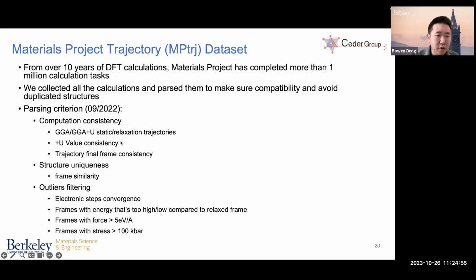And here is a list of the complicated parsing criteria that we used last year to parse this dataset. Basically, we ensure computational consistency; for example, we don't want different functionals to have inconsistent calculations, like U value inconsistency, and K-points. We also make sure of structure uniqueness by checking whether the structures are too similar to each other. And we also identify outliers by checking, for example, electronic steps and whether the frames have very weird labels.